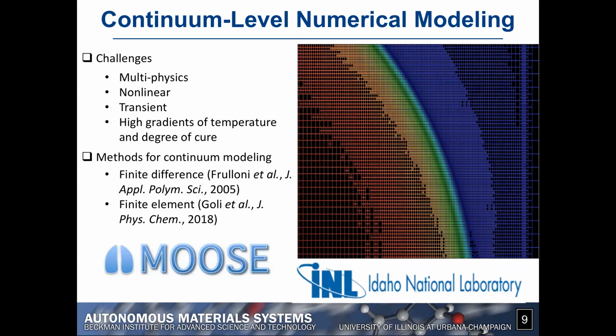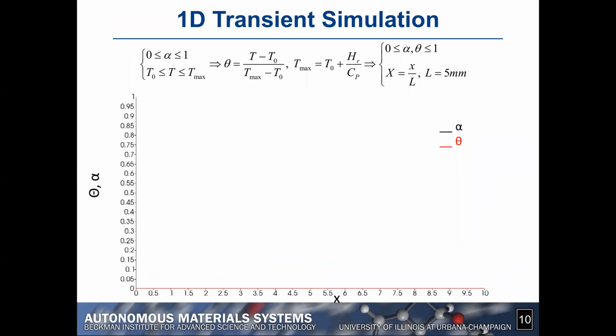So this slide here will show a typical picture of an animation of the evolution of the temperature theta, which is in a non-dimensional form. So T is the temperature, T0 is the initial temperature, and T max is the maximum temperature behind the front, and it's simply given by the relation that you have right over there. Alpha is the degree of cure, which, as I mentioned earlier, goes from 0 to 1.